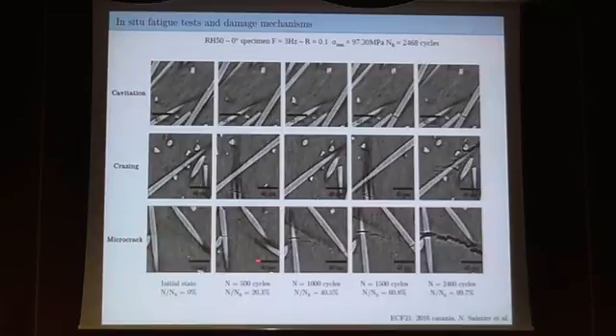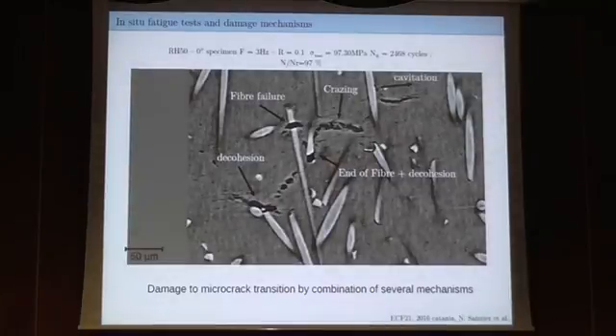And then you have micro-cracking, so you can here see a fiber that is breaking. You can see initiation of a micro-crack that is propagating within the microstructure. So that's typically the type of mechanisms that we observe, and we can read their kinetics. But the final crack occurrence, or small crack, micro-crack occurrence, appeared by the combination of different mechanisms.